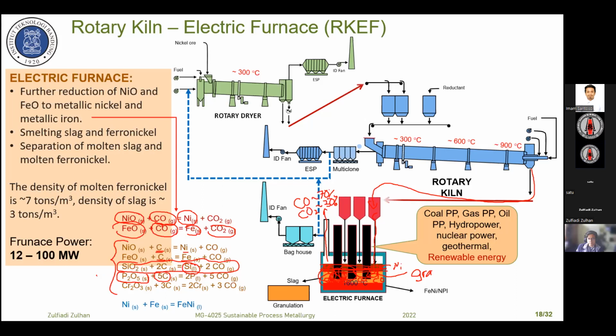Actually, we do not want this reaction to take place in the furnace, but as we heat the calcine and add the carbon, for sure, as we reduce the iron oxide to iron, this reaction also takes place, and we get these impurities into the products. Chromium also will be reduced by carbon, and we get chromium in the products, around this slag area. So the chromium oxide and silicon oxide are reduced to metal. And lastly, the product is ferronickel.